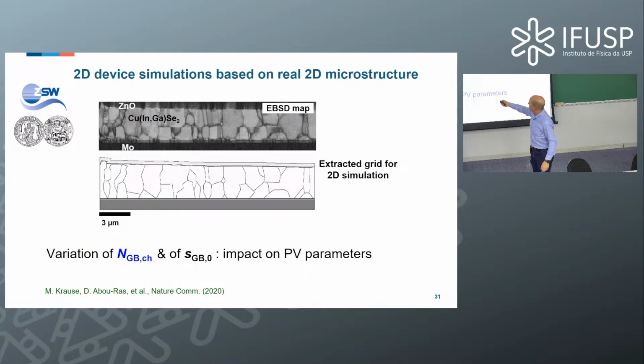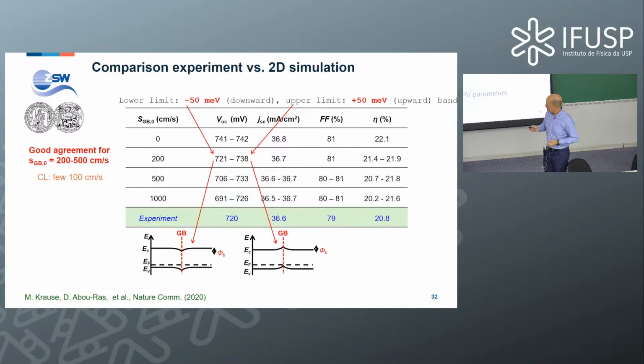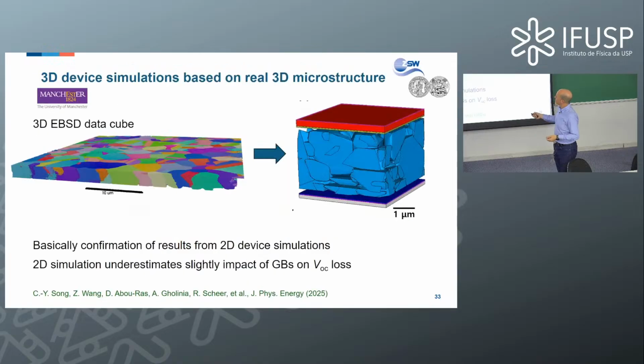And we cannot assess the microstructure in 3 dimensions here. So it means that we can also not assess the impact of grain boundaries in the real solar cell. So, of course, we have to get 3-dimensional EBSD data as a basis for a 3-dimensional device simulation, right? And that's the first time in the literature. I think there's no other example where a real microstructure was used as a basis for a 3-dimensional device